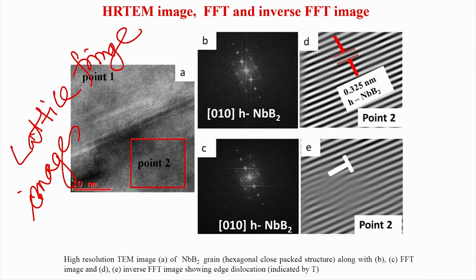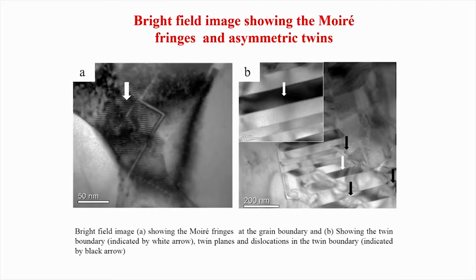Now, on the right hand side of the images, you see the FFT images as well as inverse FFT images, and from these FFT images one can find out the interplanar spacing. In the case of hexagonal niobium boride, the interplanar spacing is 0.325 nanometer, and you will also see positive edge dislocations. While you see the different lattice planes, you also see a planar defect, and the edge dislocations, which are line defects, are also present in these materials. So, this is another bright field image showing the Moiré fringes as well as the asymmetric twins.